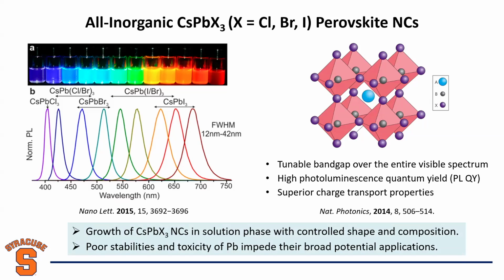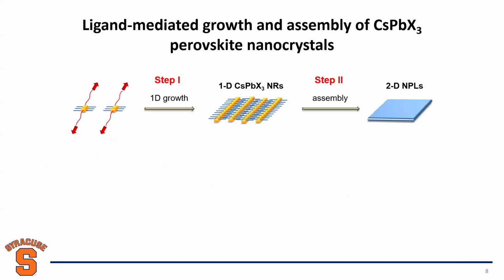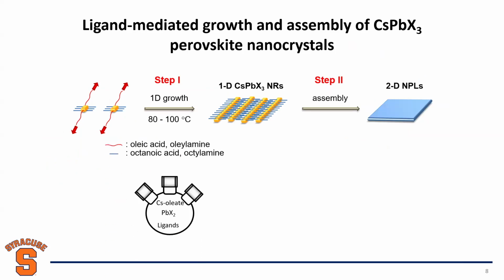So first one, how to do shape control for cubic phase perovskite nanocrystals. One thing: based on the crystal growth, we know that even with a cubic phase, if the surface energy along different facets is different, you can have different crystal growth rates, right? You can have an anisotropic nanocrystal form if you can tune the surface energy. So what we did is we developed a ligand-mediated growth and assembly strategy to grow non-spherical cubic phase perovskite nanocrystals. The idea here is that if you can selectively adsorb certain ligands on the surface, you can change the surface energy, right? What we did here is we introduced a mixture of ligands. So basically two types of ligands.